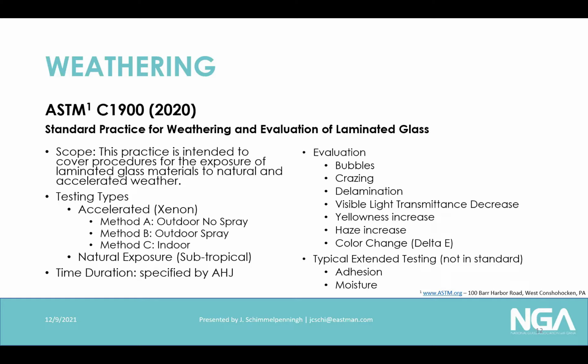The evaluation for laminated glass after weathering is looking for bubbles, which is a visual assessment, looking for crazing or delamination, and all three of those are visual assessments. And then you do measurements, looking for visible light transmission decrease, looking for yellowness increase, haze increase, or a color change, which is signified by delta E. Those last four tend to be signals of some type of polymer degradation, and that's what you're looking for. Other typical extended testing that is done, which is not in the standard, is reviewing the stability of adhesion and the moisture content of the materials over time.